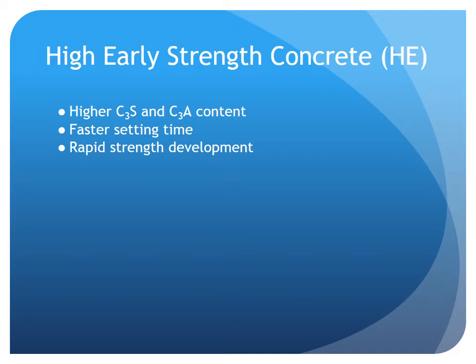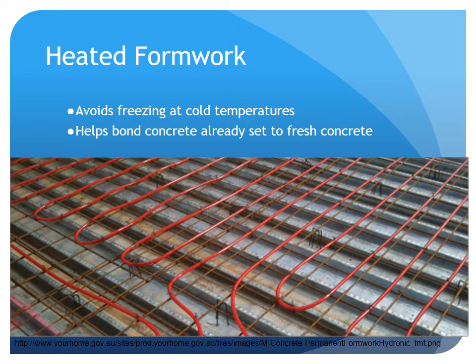Admixtures may be added to the concrete mixture to further enhance its cold weather performance. Heated formwork is another method that can be used to avoid freezing and cold weather related problems when pouring concrete. When building concrete structures, it is often necessary to pour the concrete in different stages. Fresh concrete will not bond to frozen concrete, so heated formwork can bring concrete that has already set up to temperature. An advantage to heated formwork is that it can be used with any type of concrete mixture.